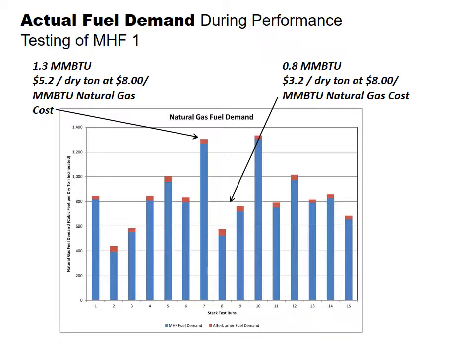During the performance test, we measured the fuel. Those little red things, hard to see, are afterburner fuel. So between the furnace and the afterburner, I just pointed to some spots on that graph. We ran from about $3 to $5 a dry ton in fuel. Furnaces, and I can give you reference after reference, run $150 to $300 a dry ton for solids handling. I'd like to see you digester guys meet that.